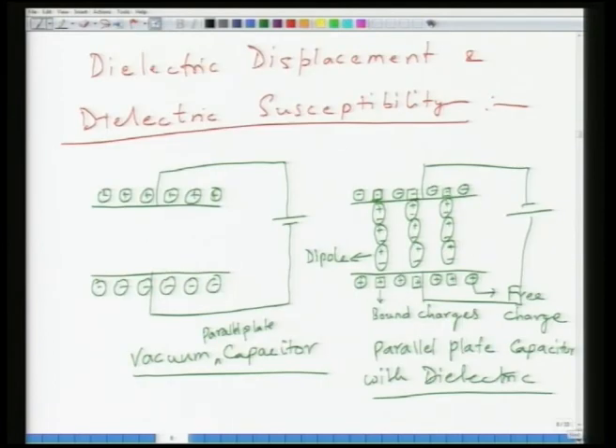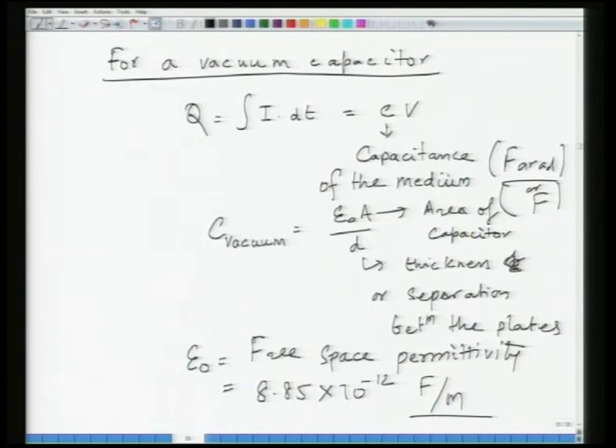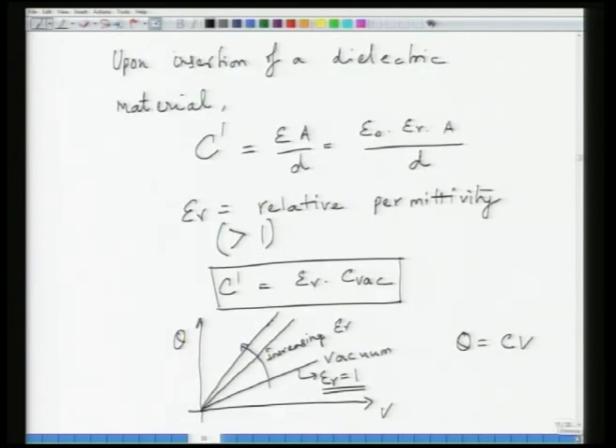And then we looked at the two configurations. One is the parallel plate capacitor without the presence of any medium, that is in vacuum, and then what happens when you insert a dielectric. If you compare these two scenarios, what you come up with is a fundamental quantity for a material, which is called relative permittivity, or some books also write it as K, which is your dielectric constant, or sometimes they write it as kappa. This is not very important. The important thing is you understand what it is. So epsilon r, by definition, when you insert a dielectric inside a vacuum capacitor, it has to increase the capacitance. As a result, epsilon r is greater than 1. What it means basically, pictorially, is that it increases the charge storage capacity of the capacitor.